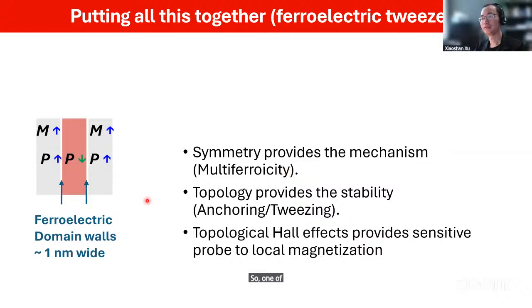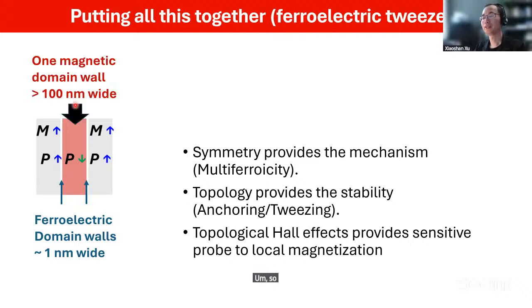So one of the easy applications, something that we can make use of in this property of the material, is to use the domain wall magnetoelectric coupling. You can imagine you have a pair of domain walls, polarization up on the side and down in the middle, and you have these domain walls. That's all normal in the sense of ferroelectrics. But remember, we said the magnetic domain walls are much, much wider. So all we have to do is to make the middle thin enough, comparable to the magnetic domain wall. So essentially, we can use the two ferroelectric domains to determine or to control the magnetism in the middle. We call this a ferroelectric tweezer.